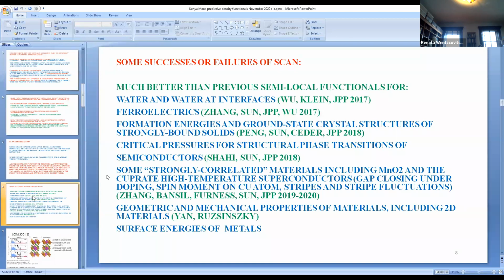The gap closes under doping. We also get the right spin moment on the copper atom. We get stripes and stripe fluctuations, and many other things, from the SCAN functional without any additional correction or empirical input. You can also get geometric and mechanical properties of materials, including two-dimensional materials, and you can get surface energies of metals accurately.